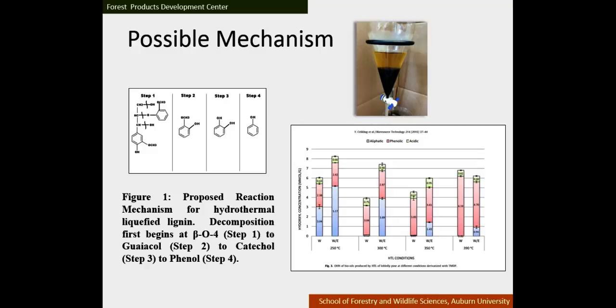As you increase the temperature, you go from step 1 to step 2. You increase your temperature, you go to step 3. And eventually when you get to step 4, you end up with a phenolic. And so as you increase your temperatures, lo and behold, you end up with more phenolics. So that's my hypothesis about what's going on. But keep in mind, this is a very simplified hypothesis because there are hundreds of chemical compounds in bio-oil. But this is what I came up with.